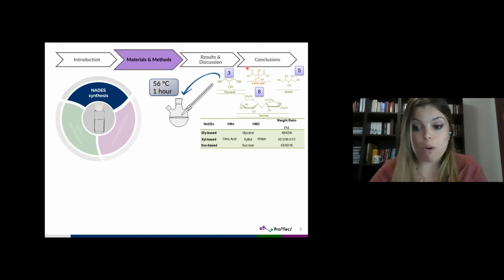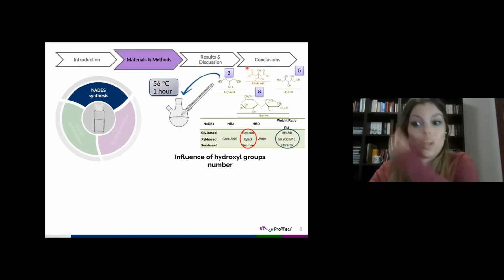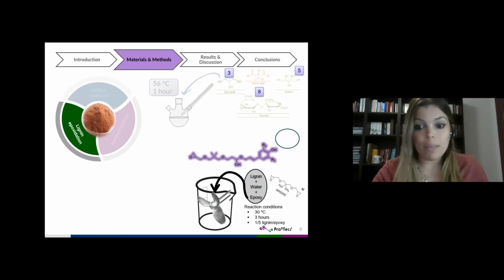Moreover, as can be seen in the table, different amounts of these reagents and water were required to obtain stable liquids at room temperature, which also allows modifying the viscosity properties of this blend, I mean with the addition of water. Therefore, we are going to analyze the influence of the hydroxyl group number on the final properties of our thickened formulation. Okay. Well, in the second step, lignocellulosic material was chemically modified through epoxidation,